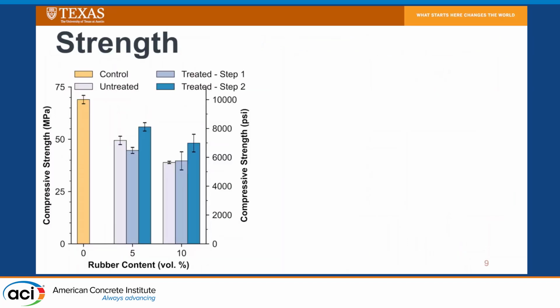So over here, this is showing you the results of compressive strength with our control sample. So this is a sample that contains only natural sand, so river sand. So these are mortar samples. And then our untreated rubber sample here at a 5% and 10% volume. I forgot you can't see what I'm doing. 5% and 10% volume. And then the light blue is showing you what happens after the first step treatment, and the darker blue one is showing you what happens after the second treatment step.